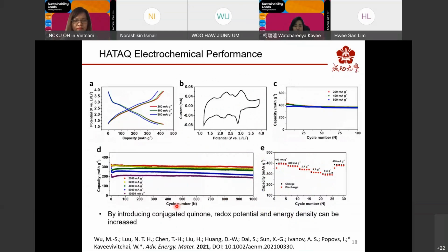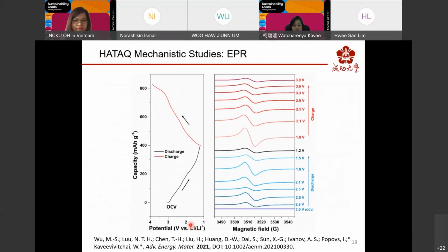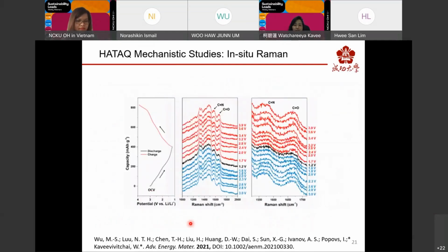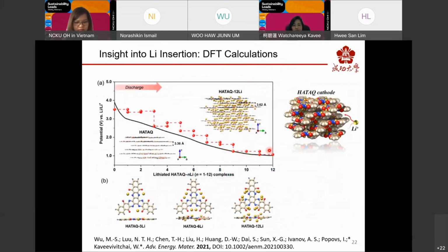And by introducing conjugated quinone to the structure, we found that the redox potential as well as energy density can be significantly increased. We use EPR, XPS, as well as in situ Raman in order to understand the redox mechanism. The characterization techniques confirm that both the CN group and CO group participate in the redox reaction, interacting with lithium ion. We also have DFT calculations to identify the position where lithium will be inserted into the structure, such as this. And we confirm that the compound can be inserted with up to 12 lithium.